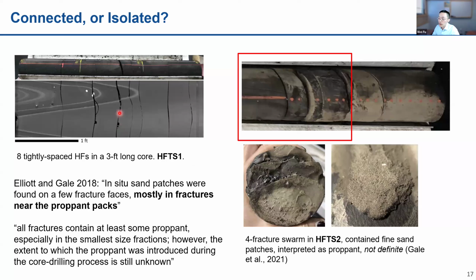We've already seen this photo: 8 tightly spaced hydraulic fractures. As Elliott and Gale put it in 2018, they found in situ sand patches on a few of the fracture faces, mostly in fractures near the proppant packs. Where the proppant packs exist, it most likely indicates a main fracture that accepts a lot of proppant, and then near the main fractures, they find fractures with proppant patches. Although there is a debatable observation: they actually observed hundreds of fractures in the retrieved core samples, and all the fractures contain at least some proppant, especially the very small ones. Whether this is due to core drilling or post-processing of the samples is still unknown. So that's a debatable observation, just to put it here to be rigorous.